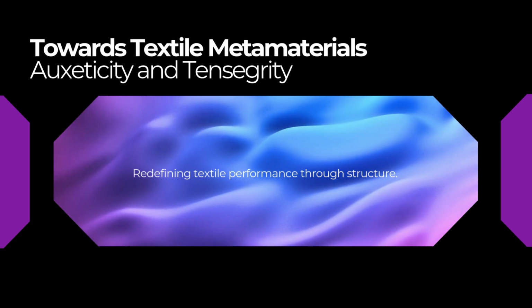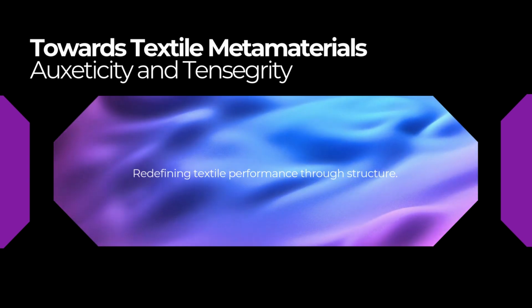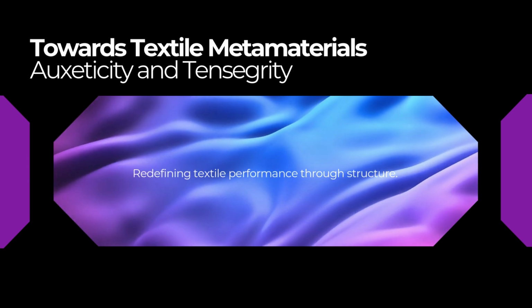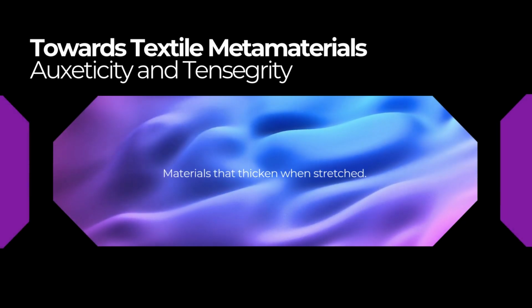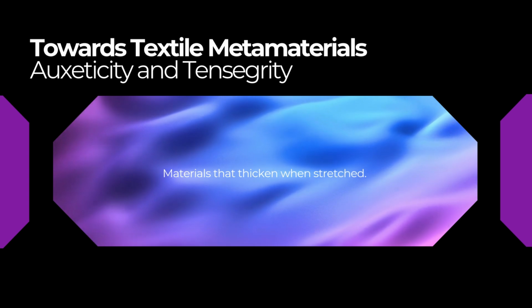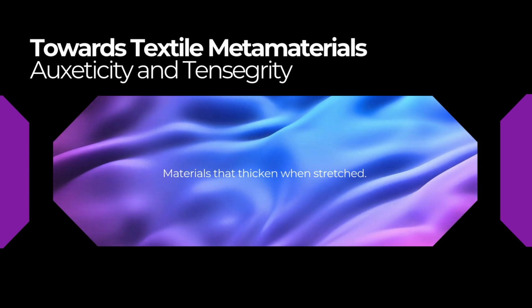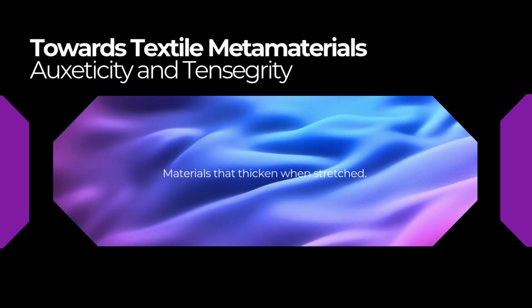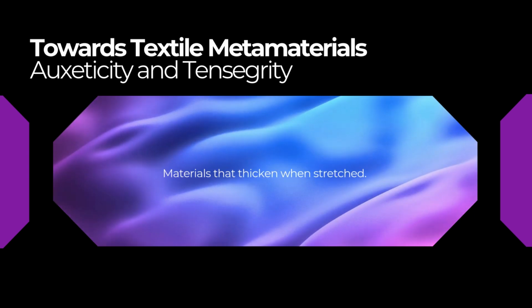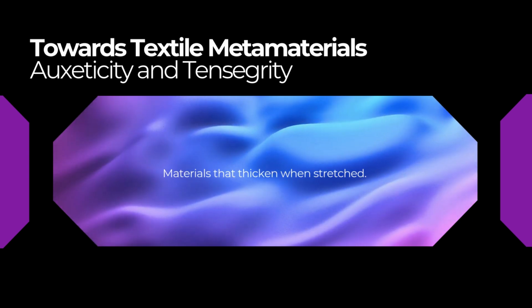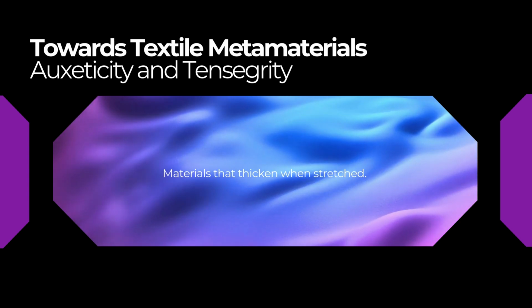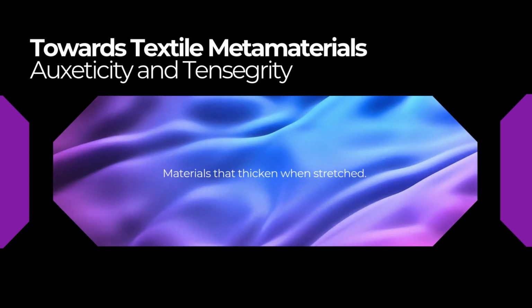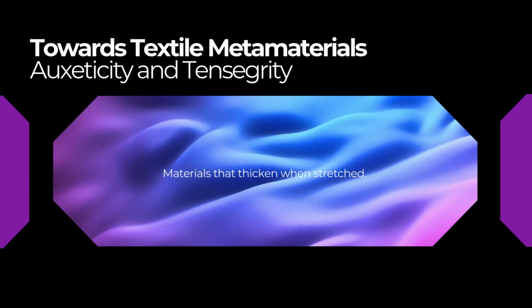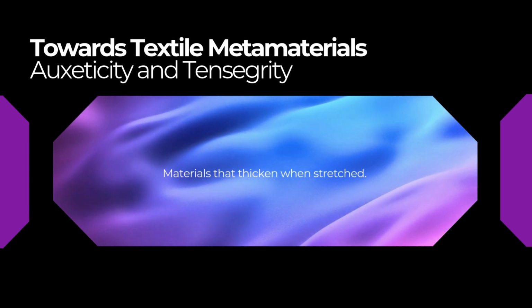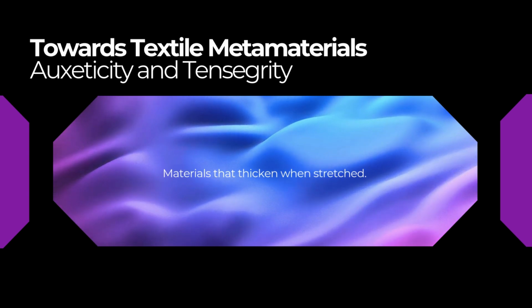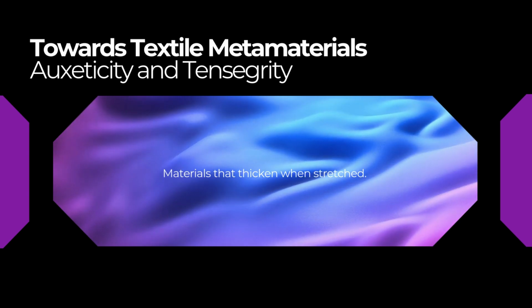A critical feature. And if we connect this back to the mechanical data, the fact that the material finds a new, stable, relaxed configuration after high strain, that perfectly supports the idea of the felt acting as a multistable tensegrity structure. Multistable, meaning it can exist in more than one stable state. Correct. You put in enough energy, that 20% axial strain, and you activate a conversion to a new network configuration. It's like a complex puzzle clicking into a different, equally stable arrangement. The system restabilizes itself, just in a damaged state.